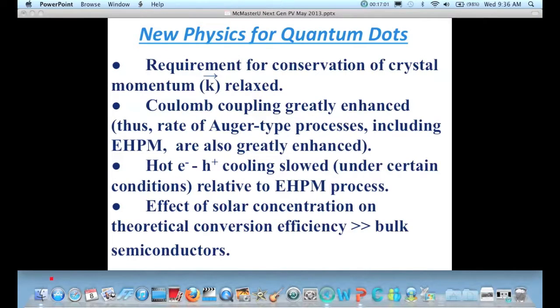But with quantum dots, you have some new physics that arise. First of all, you don't have to conserve momentum, just energy, because you can think of it in simple terms that when you confine the electron and the hole to a small region of space, according to the Heisenberg uncertainty principle, you know where the electron is, therefore you don't know the momentum. So momentum is not a good quantum number, and you relax the requirement to conserve momentum. Secondly, because you have the electrons and holes very close together, these quantum dots are typically 1 to 10 nanometers in size, which means that you enhance the Coulomb interaction between the electron and the hole way, way above what occurs in free carriers in the bulk material. And the multiplication process is a type of Auger process, and so it's enhanced in quantum dots.